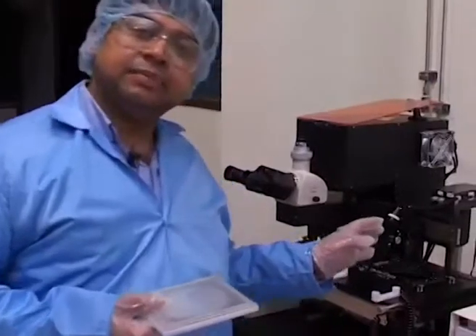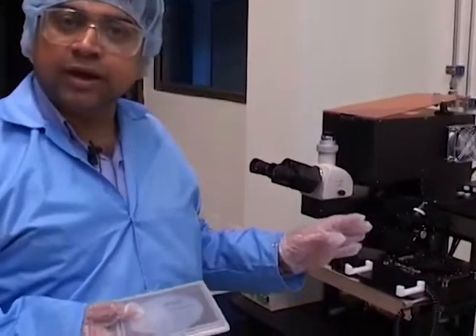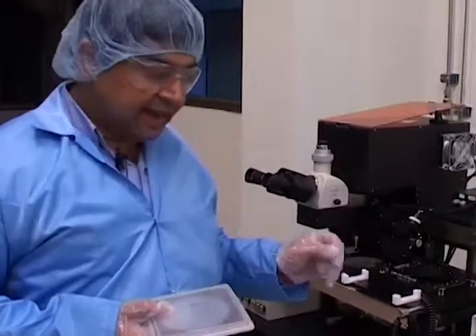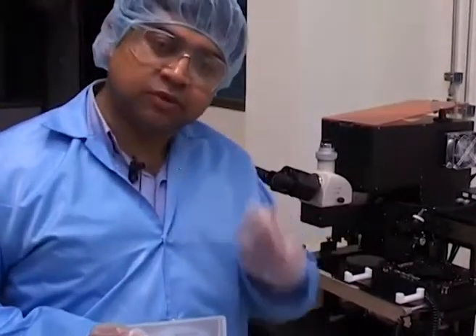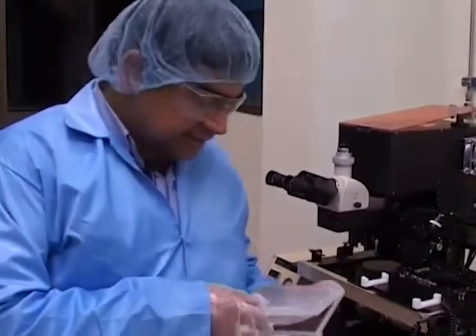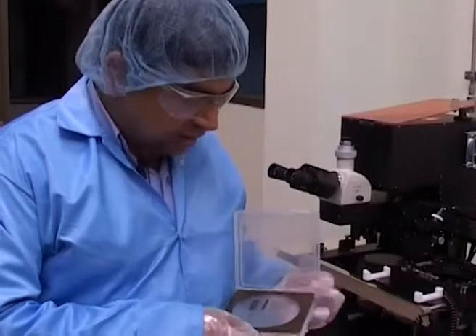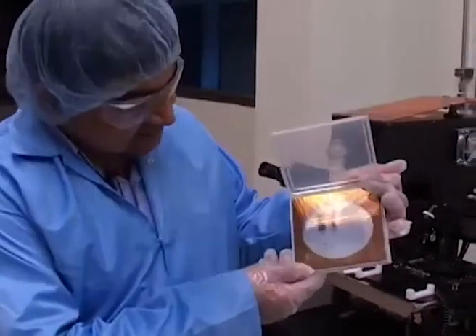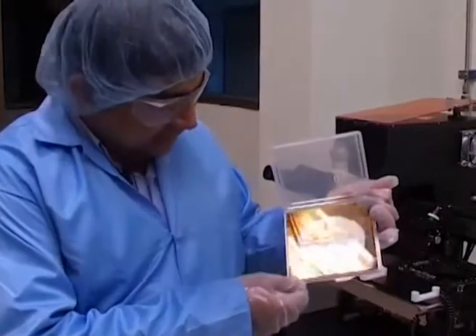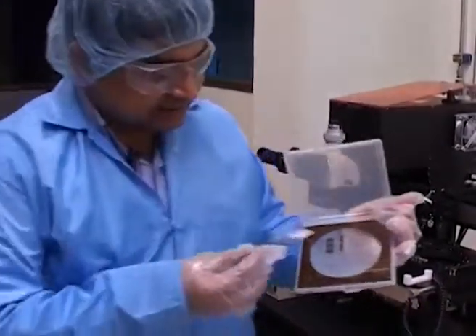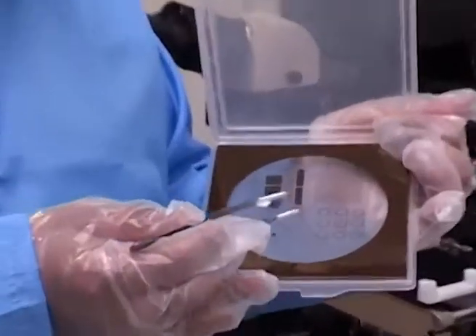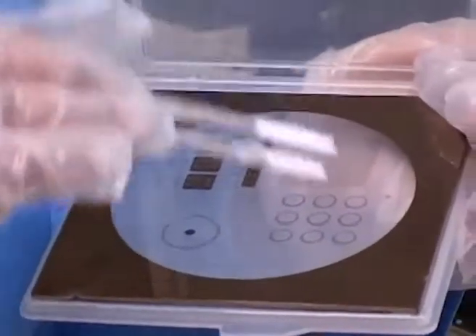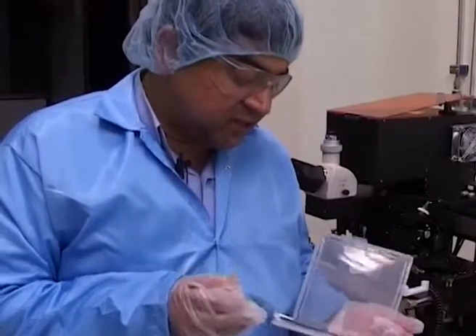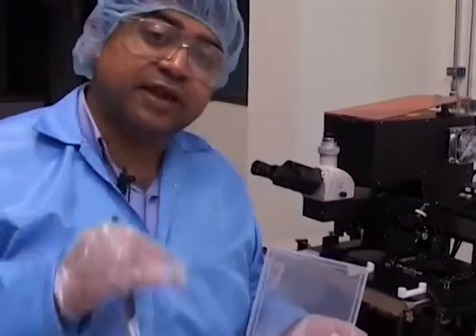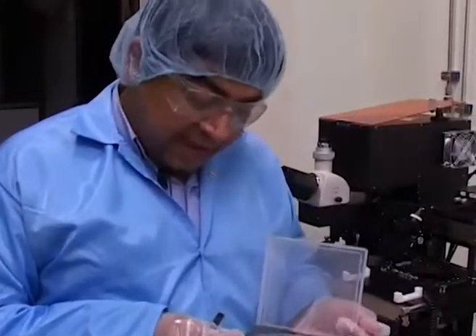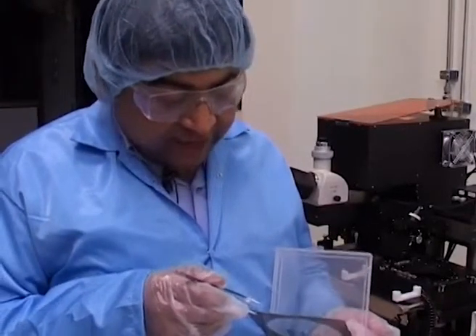So essentially this is called the photolithography equipment, and this is used for exposure of the resist to very characteristic frequency of light, mostly in the UV area. Essentially here what you do is to use something called a hard mask, which you can see right here. This is actually a glass chrome mask, where you can see very closely that some of these features really are at the micron scale. And these have been made using laser etching in a film of chrome, and this particular side which has the coating really sits with the wafer, being aligned with the wafer. Because otherwise, if you have the other side sitting in proximity to the wafer, there are diffraction effects.